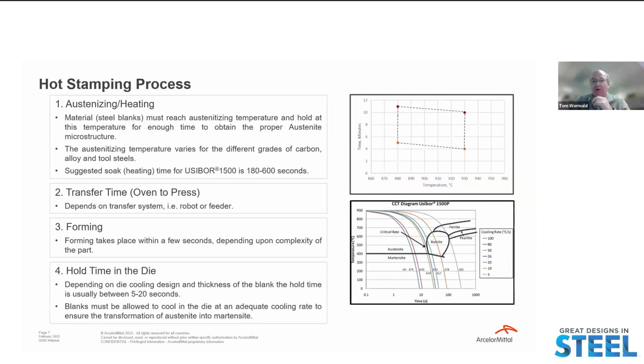As mentioned, the hot stamping process is largely driven by the desire to ensure complete transformation of the microstructure of the steel. A window of time and temperature is established to ensure complete austenitic microstructure is reached in the heating furnace. Transfer time is minimized between the oven and the press, an automated system that occurs in a matter of seconds. A critical component to achieving consistent end properties is controlling the cooling and quench rate in the die, and that's guided by the CCT diagram you see on the right.